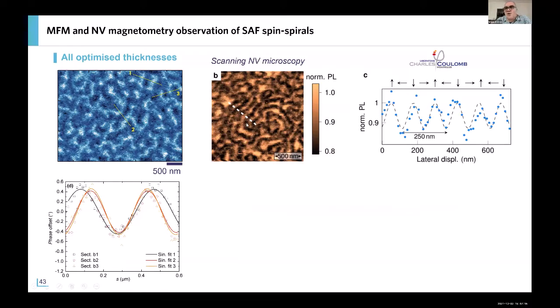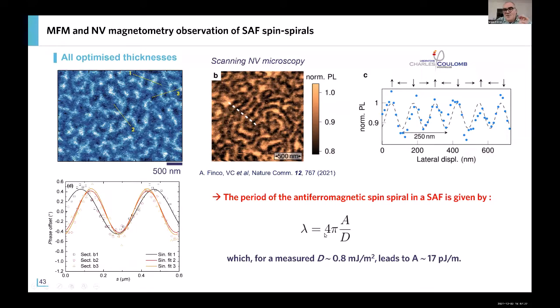And we can quantify this by taking line sections, and we get this sinusoidal behavior. And in fact, we confirm this in collaboration with Vincent Jacques by scanning NV microscopy, where there is no magnetic tip. We get exactly the same periodicity for the spin spiral. And very interestingly, the expression of the periodicity is very simple for a spin spiral in a SAF, because as you see, it's equal to the ratio of the exchange stiffness parameter over the Dzyaloshinskii-Moriya interaction. And as we can measure the DMI, we can then extract from this periodicity the exchange interaction in this thin film, which is a parameter that is very important, but not very easy to quantify.